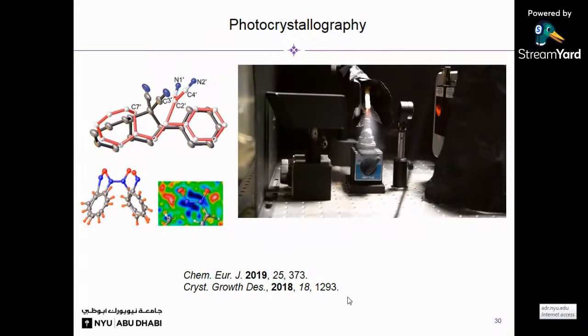And apart from that, I am also actively working on photocrystallography. In our BSc or master's days, we used to study reactive intermediates, like carbenes and ylides. The only way to characterize those reactive intermediates was by using NMR or UV spectroscopy. But when you want to determine the three-dimensional structure of those materials in the solid state, you need to excite the molecules with some kind of laser. So in our lab, we combine lasers and X-rays, and we can determine short-lived reactive intermediates in their crystalline structure.